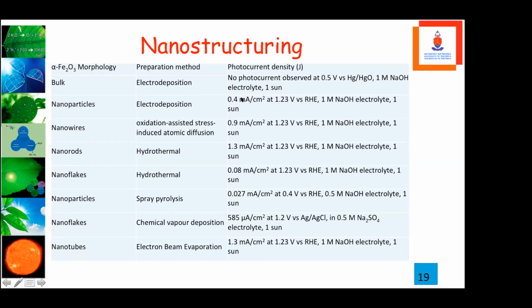Then we have also achieved nanoparticles, and you can see that our photocurrent is growing gradually from 0.5 milliamps, 0.9 milliamps, to 1.3 when you use nanorods, after we have grown those nanorods using hydrothermal methods. And then with our nanoflakes, we have just achieved an experiment where we have made the nanoflakes, but the photocurrent is too small. In another experiment in the lab where we used the nanoflakes, it was improved a little bit, but we still believe that the nanotubes and the nanorods are doing better as compared to other nanoparticles.